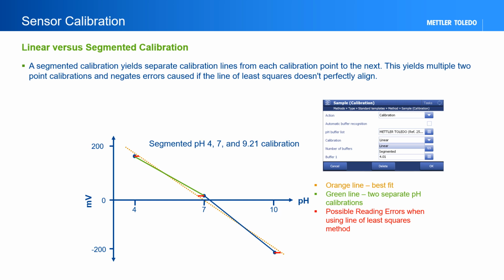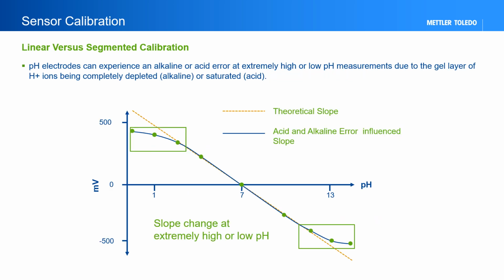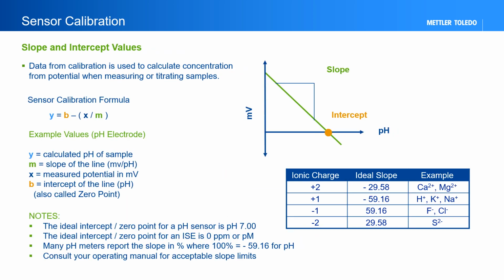In extremely high or low pH solutions, electrodes can experience an alkali or acid error. This is caused by either too many hydrogen ions present in solution or too little hydrogen ions in and on the glass pH bulb. Near these pH values, segmented calibrations are most useful as the calibration line deviates from a theoretical straight line. Data from the calibration is used to calculate concentration from potential when measuring or titrating samples. This is seen in the example graph and line equation for a pH electrode.